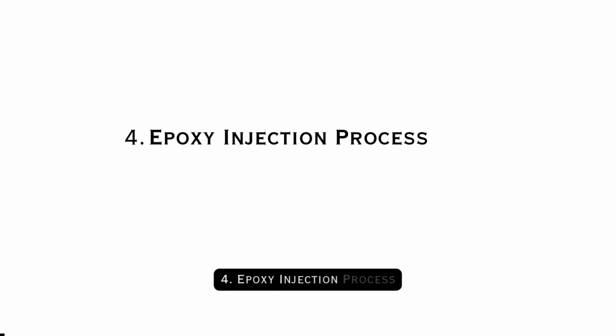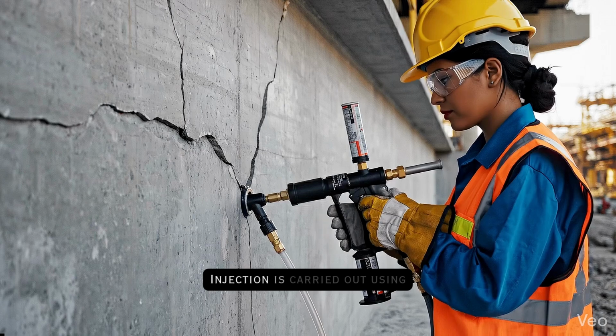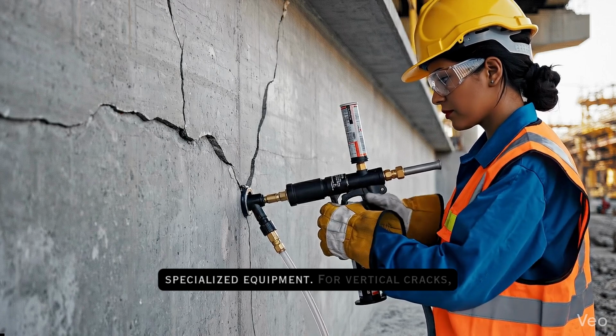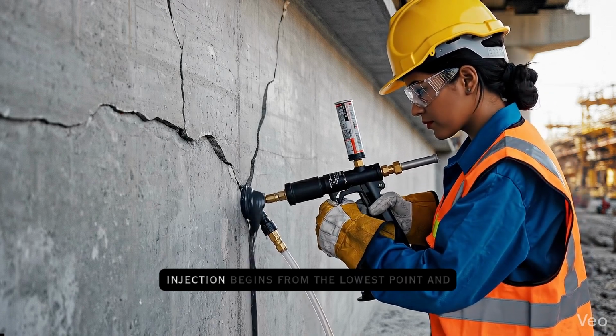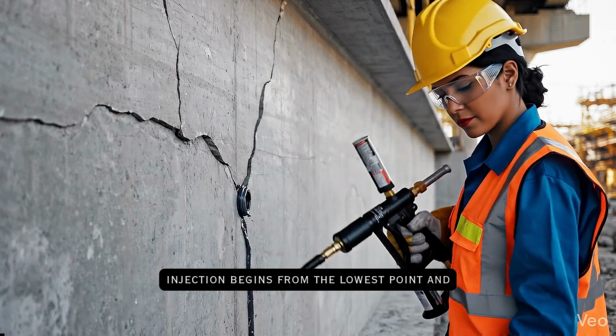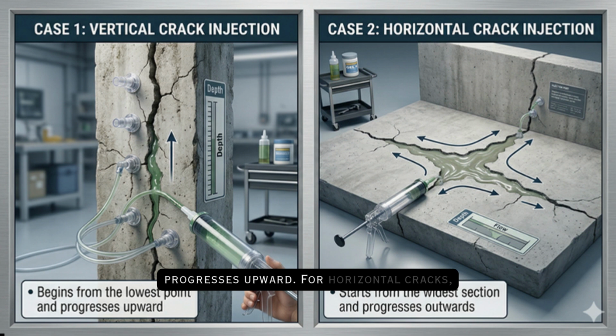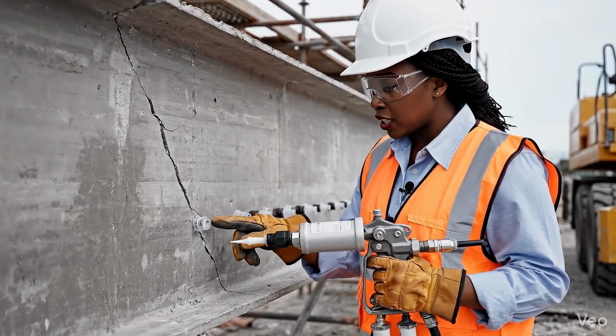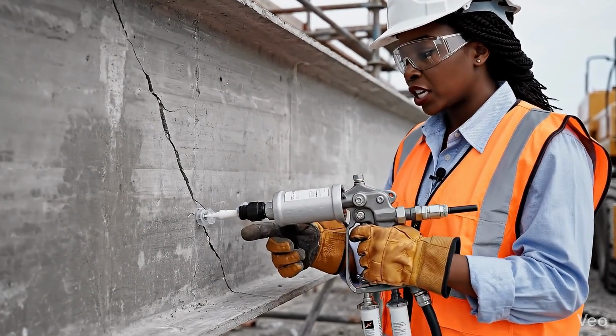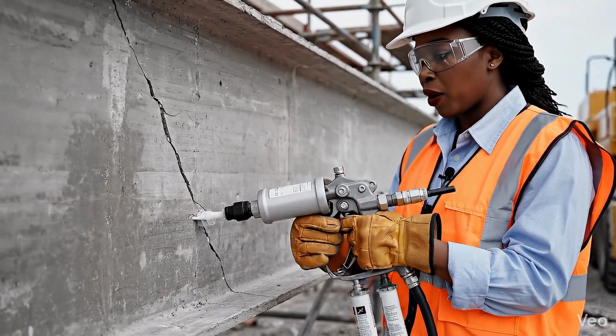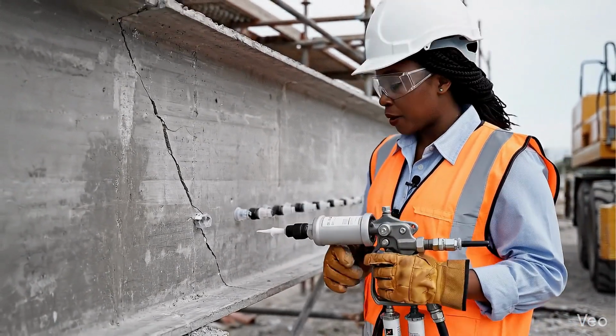4. Epoxy injection process. Injection is carried out using specialized equipment. For vertical cracks, injection begins from the lowest point and progresses upward. For horizontal cracks, injection usually starts from the widest section. We begin by inserting the nozzle into the port and applying pressure. You can see the epoxy filling the void. Now we move to the next port.